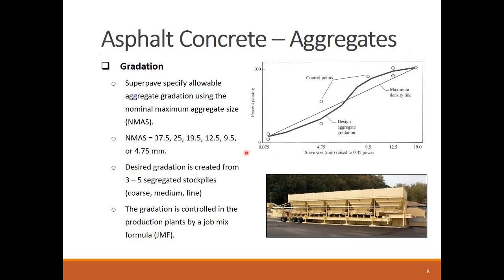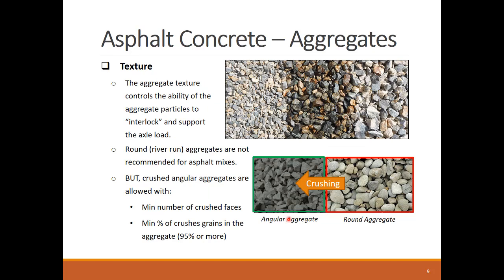NMAS design values in Superpave are 37.5, 25, 19.5, 12.5, 9.5, or 4.75 millimeters. In asphalt plants, the aggregate gradation requirement is achieved by mixing aggregates from three to five segregated stockpiles that follow a coarse, medium, and fine classification of the aggregates. The aggregate proportions from these stockpiles are determined to create a job mix formula that is followed during the asphalt mixing.